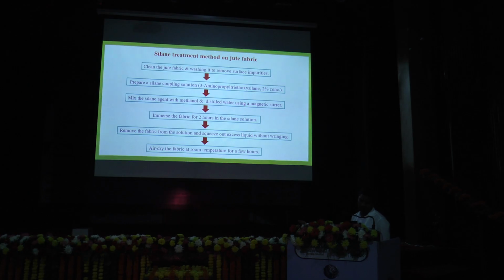Then mix this silane agent with methanol and distilled water using a magnetic stirrer. Then immerse the fabric for 2 hours in the silane solution. Then remove the fabric from the solution and squeeze out excess liquid without using force. Then air dry the fabric at room temperature for a few hours.